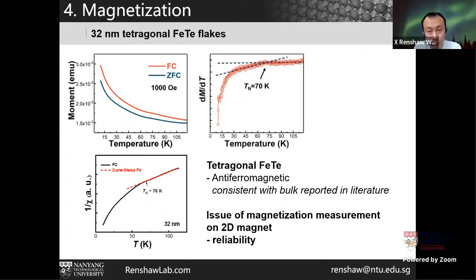If you look at the data, especially the dM/dT, we can maybe see a little bit of a Néel temperature, which is consistent with the reported literature in bulk, where the tetragonal FeTe is supposed to be antiferromagnetic. Of course, we did some preliminary analysis. We see, okay, it's an antiferromagnetic phase.